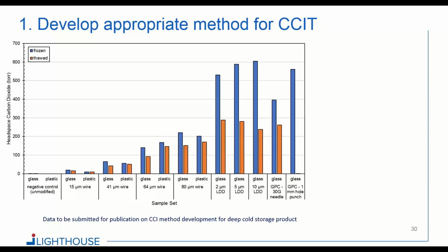And so here you see a number of different types of positive controls. You see some wires, different size wires here being labeled. Those are samples that have these wires in between the rubber stopper and the vial neck. So you don't know for sure if that causes a CCI defect, but it probably will. On the right-hand side, you see some LDDs. Those are laser drilled holes that are in the glass body of the vial, and you can get holes drilled that are certified to a certain dimension. So you see here 2 micron, 5 micron, 10 micron. And on the far right, you see some gross defects. So we include all of these types of positive controls in our method developments.